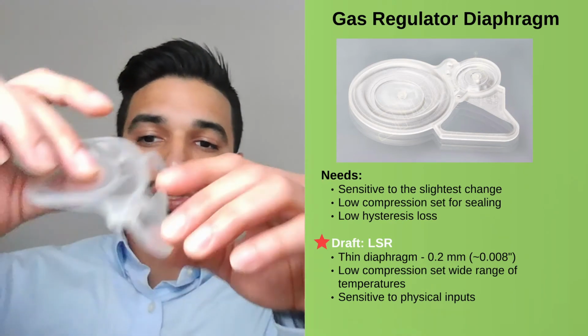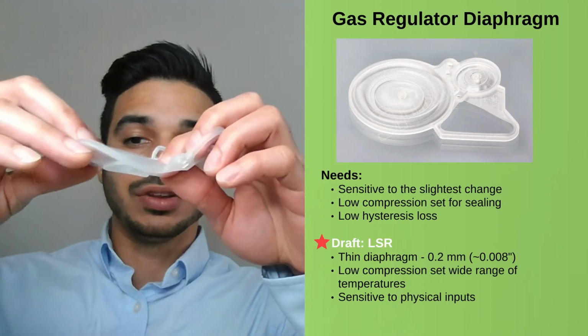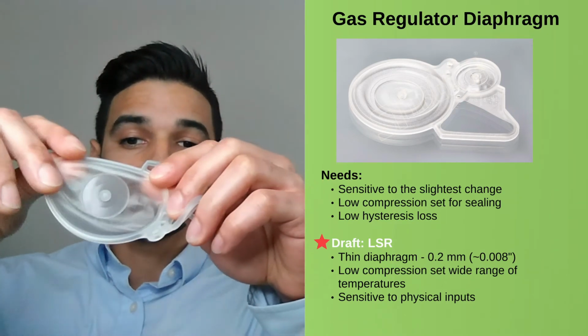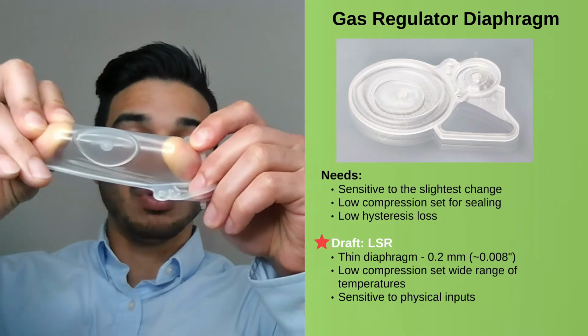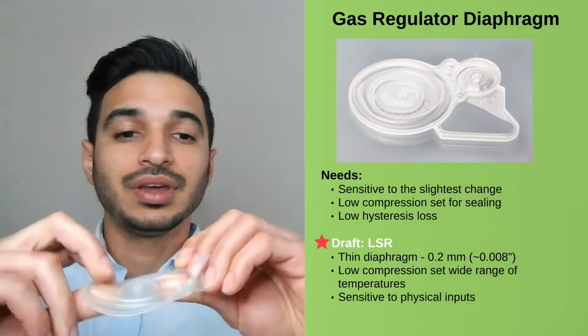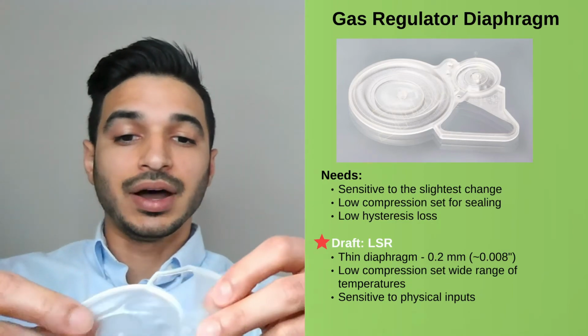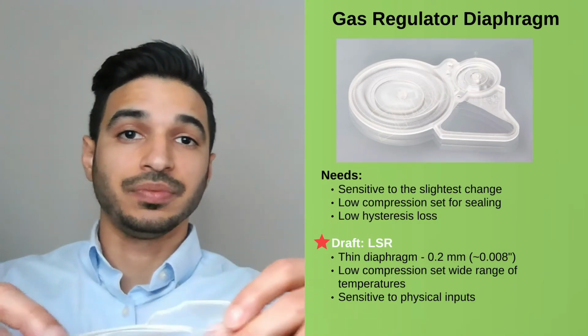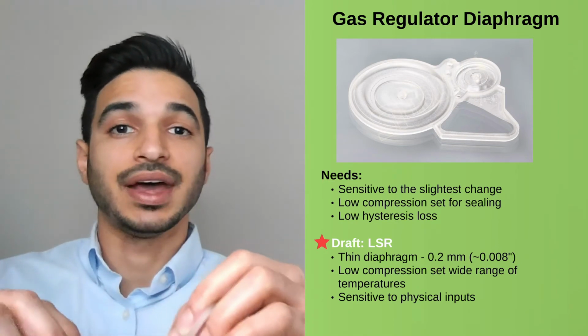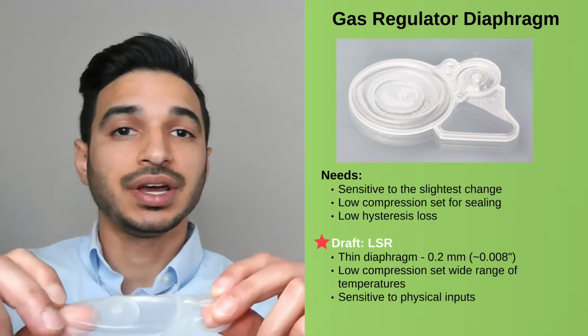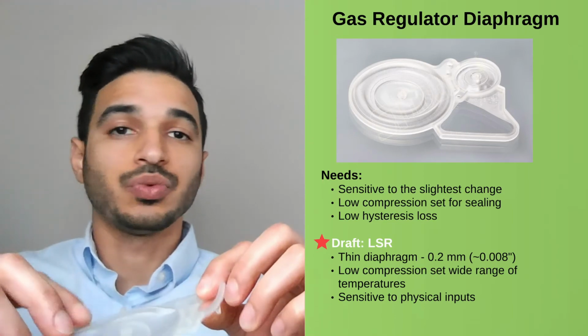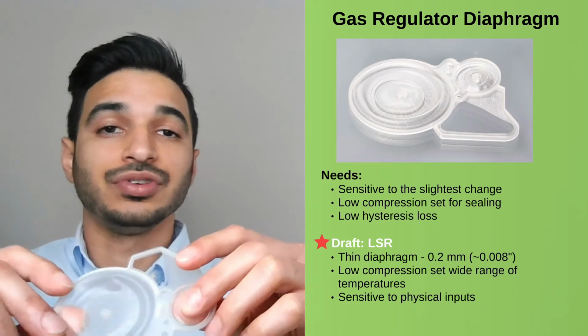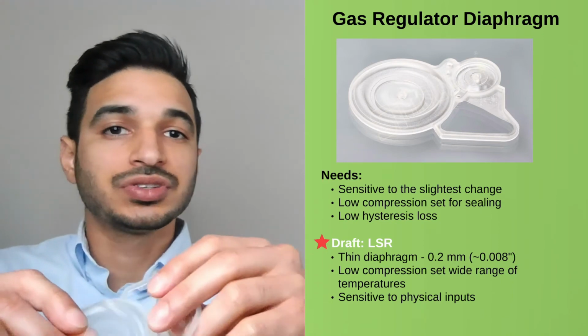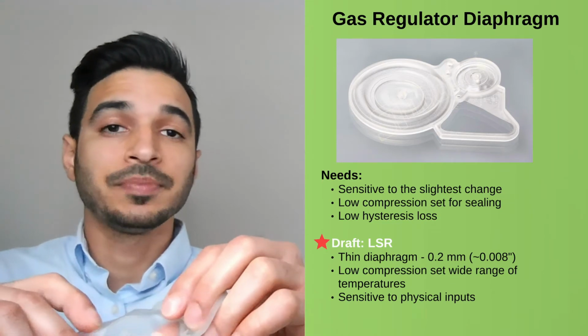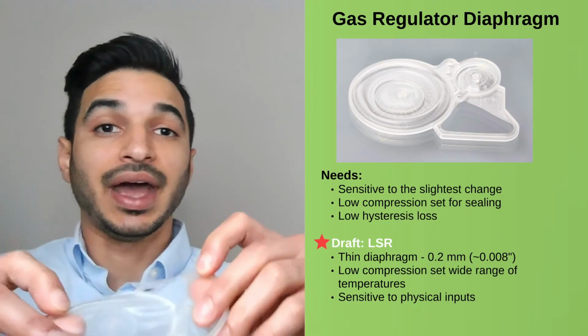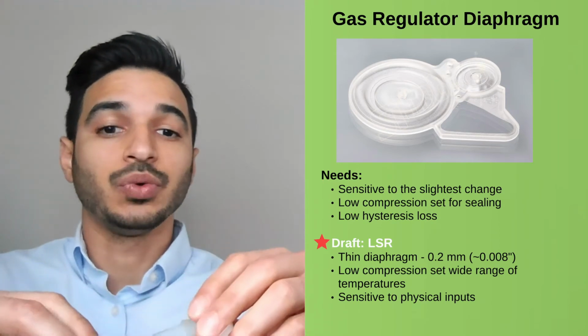So as I show you in the diaphragm, it's got a very thin profile. And so for the durometer selected and the response needed, the diaphragm is actually 0.2 millimeters in thickness, or around 0.008 of an inch. And this is very hard to do with a higher viscosity material. And so LSR was the only material that could achieve that thinness. It also needed to have a very low compression set over a wide set of temperatures. So your water heater, your fireplace, or your gas stove may be in some conditions that may be very cold or very hot. And so that seal needs to be maintained as the temperatures are ranging and moving quickly.